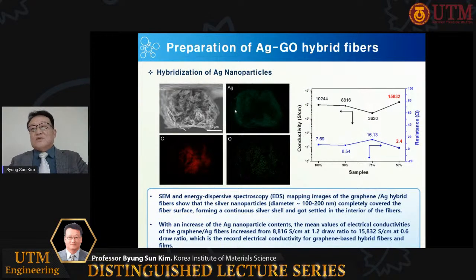In hybridization of silver nanoparticles, SEM and the energy dispersive spectroscopy mapping images of the graphene silver hybrid fibers show that the silver nanoparticles of about 100 to 200 nanometers in diameter have completely covered the fiber surface, forming a continuous silver shell and settled in the interior of the fibers. Next slide, please.